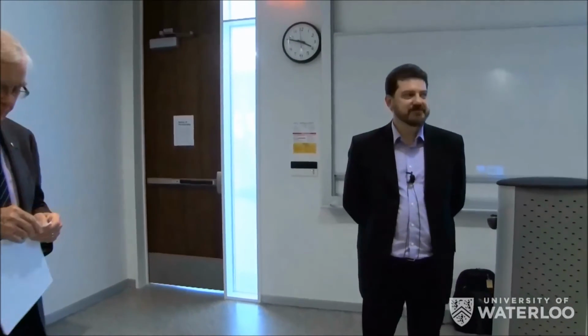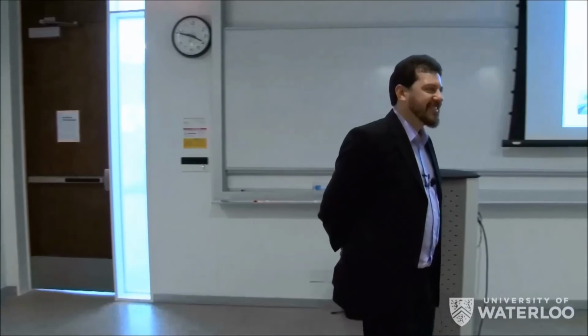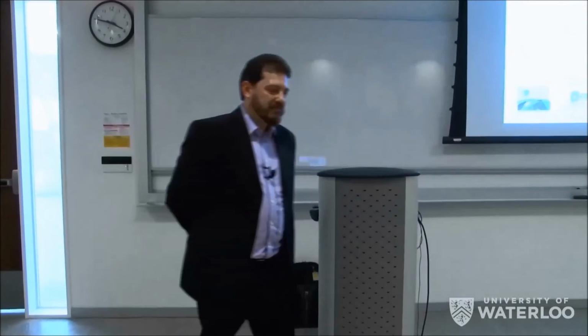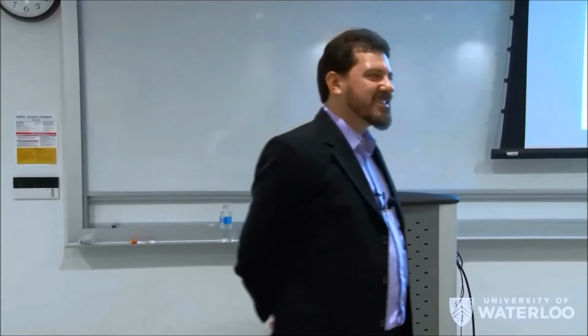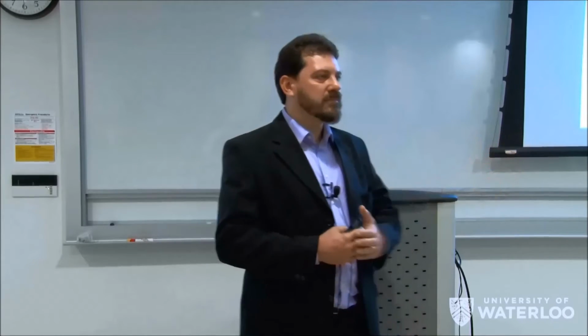Yes, Michael. Just curious, how do you engineer the strain there? Okay, so we have a few recipes. One is really to look into data that failed. If you get papers from the 60s and 70s where people were trying to get the stress configuration and the stress into the material, you can clearly see the combinations that fail miserably. One of those is titanium chromium. For chromium, for instance, you can go from tensile to compressive stress by simply changing the pressure at which you deposit the chromium.